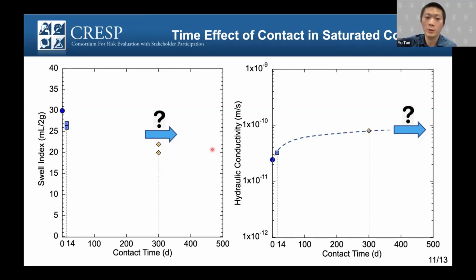But the longest time that we can do depends on when I will graduate. I would not spend more than eight years in those tests for my PhD. So it's still limited. So following Nick's suggestion, our hypothesis is that the interaction between the concrete and the bentonite depends on the cation exchange between the concrete and the bentonite. So we can wash the cation in the concrete out to get the pure water in the concrete and run the swell index test.